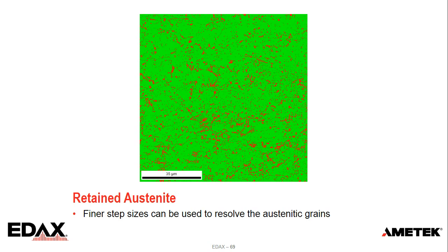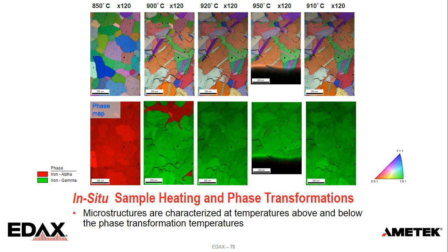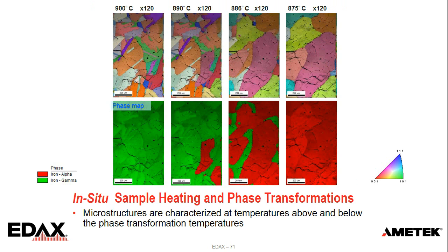And of course, through all this, one of the things we can do is in situ analysis. So this is an example. This is work by Suzuki-san over in Japan, where he's done heating of a steel through the transition temperature. So we start here in the red, we come up through it, it transforms into the green phase, and then as we go back down, it comes back to the red phase. And so we can control temperatures going up to the 1,000 degree C range to be able to observe these transformations in situ.